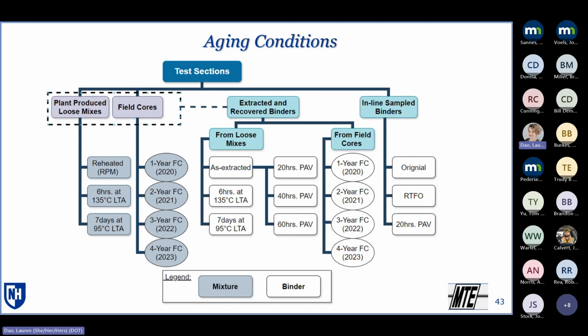Okay, those as extracted binders were also put through 20, 40, and 60 hours of PAV aging, as well as the extractions from the different loose mix aging conditions. For the field cores, we also have extracted the top ½ inch for each year. With an asterisk, 3rd-year field cores, we had some issues with some contamination. So you'll see we don't have the results for those 3-year field cores, but we've got 1, 2, and 4. And then the inline sample binders were also tested, original RTFO and PAV aging conditions.